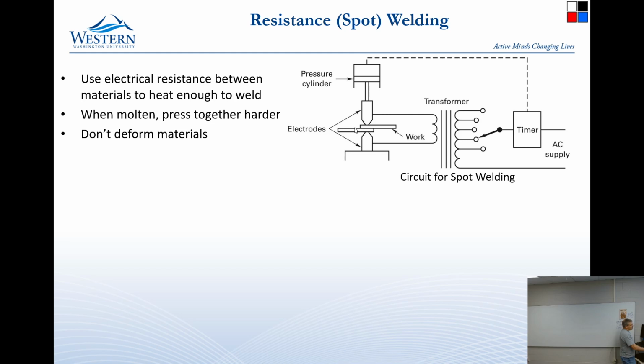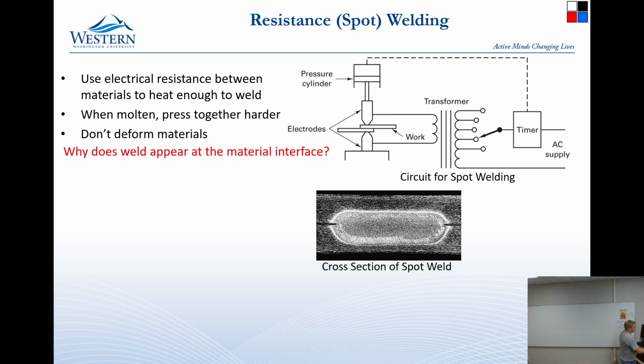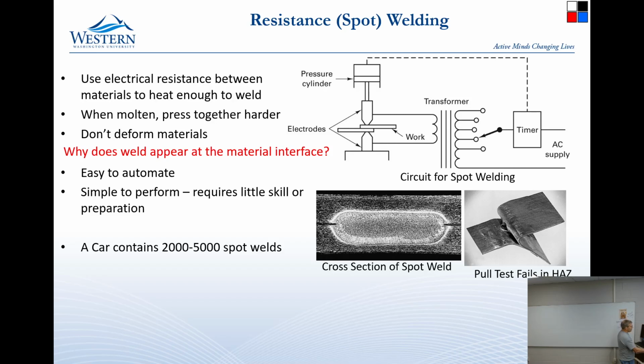So this is a super easy way to weld things, and it's great for lots of things. It requires the materials to overlap, so you pay some weight penalty for this. Also, it is only welded at the little spot that you did. When they do welding on a car, there are thousands of spot welds, because they do all these welds all along. A car contains 2,000 to 5,000 spot welds. The way that you test them is you pull them apart, and it looks like a tear test if you were checking an adhesive material. It's essentially the same thing, and you are expecting the material to fail in the heat affected zone.